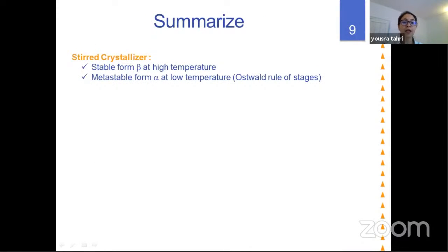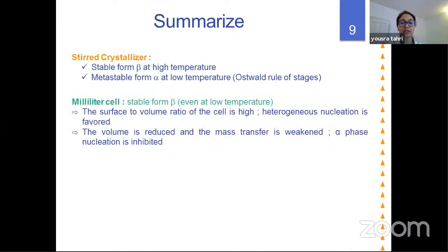So to sum up, in the stirred crystallizer, we have the crystallization of the beta phase at high temperature, and the metastable phase alpha was observed at low temperature. We deduced that the system obeyed the Ostwald rule of stages at low temperatures, while in the milliliter cell, we only observed the stable phase beta, even at low temperatures. This may be caused by the high surface to volume ratio, which promotes the heterogeneous nucleation, and the heterogeneous nucleation favors the appearance of the stable phase. Also, the volume is reduced and the mass transfer is weakened, so somehow the alpha phase nucleation was inhibited.